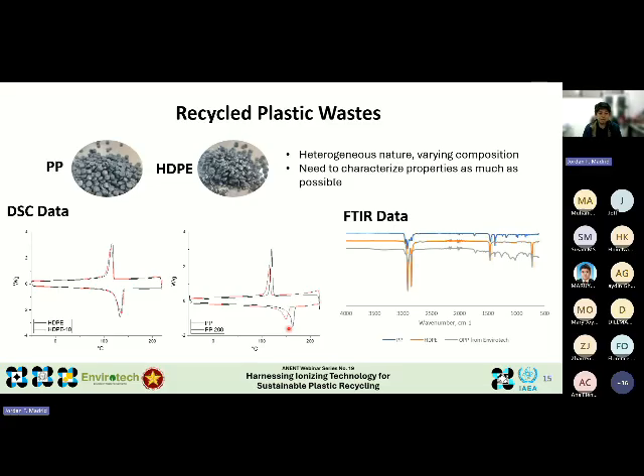From FTIR, we were also able to confirm the characteristic chemical bonds of polypropylene and high density polyethylene. However, we also observed some extraneous peaks that we attribute most probably to impurities because these plastics are already recycled.